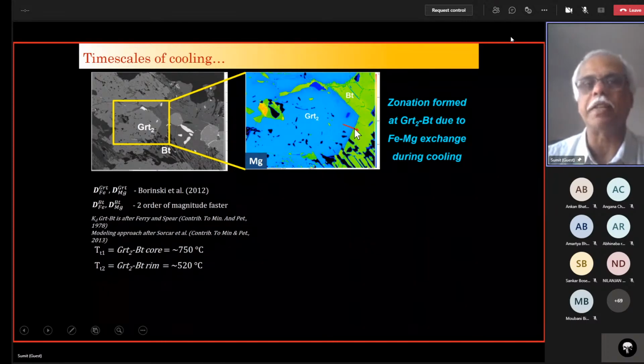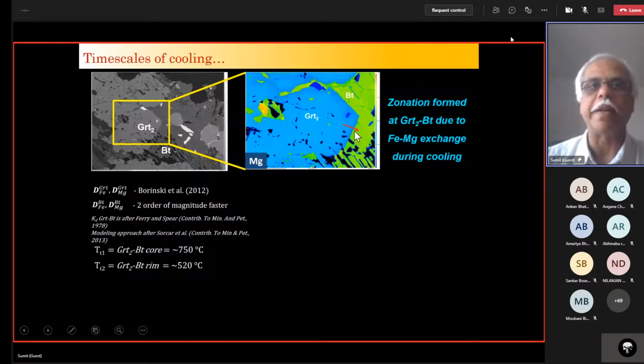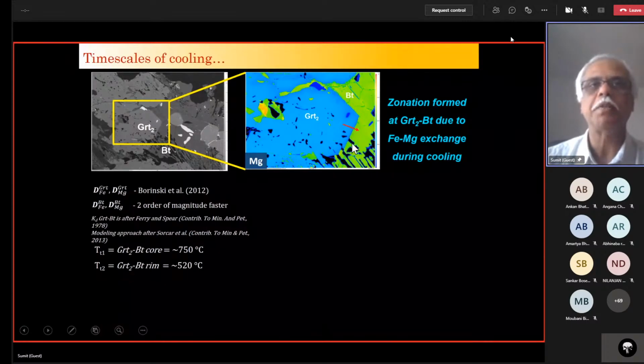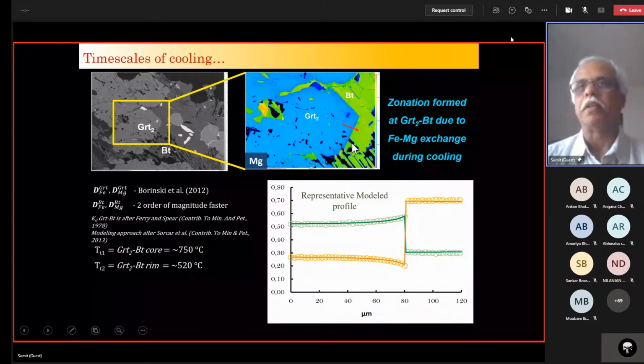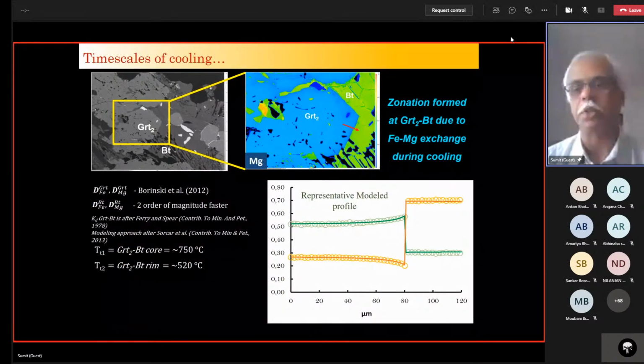When you model that, you'll get the cooling history over that range of temperature. And this is an example of what it looks like. The circles are now measured points from an electron microprobe, and the lines are the calculated fits that you get by fitting such a diffusion model to the data.